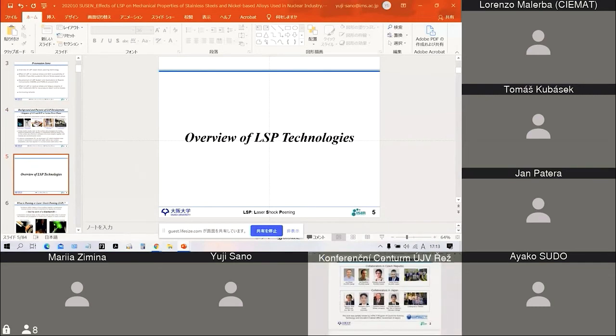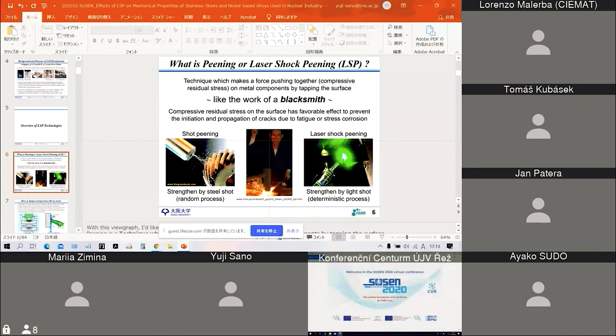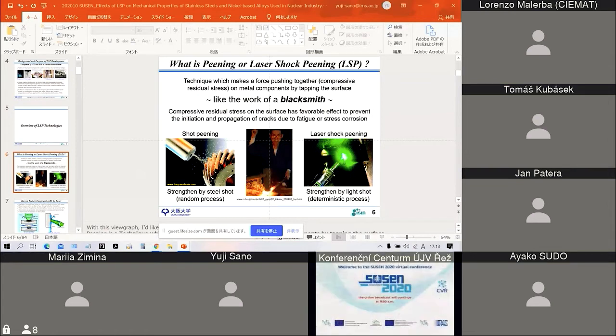So I move to the LSP technologies. This graph explains what peening, or laser shock peening, is. Peening is a technique which makes a force pushing together. It means inducing compressive residual stress on material components by tapping the surface, like the work of a blacksmith. Compressive residual stress on the surface has a favorable effect to prevent the initiation and propagation of cracks due to fatigue or stress corrosion.